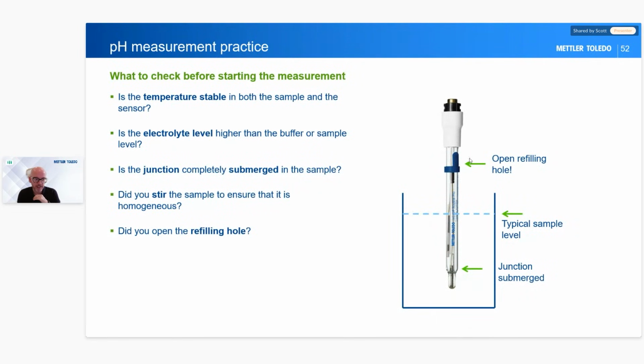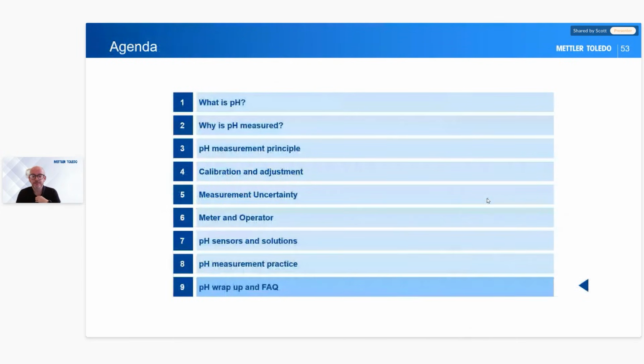And then if you do have a liquid electrolyte, it's really important you open this hole, because this hole can cause a vacuum inside the electrolyte if it's not opened. So during measurement, you open it and then you close it again when measurement's finished. Something to remember. Okay, so that hopefully wraps up nearly everything today.